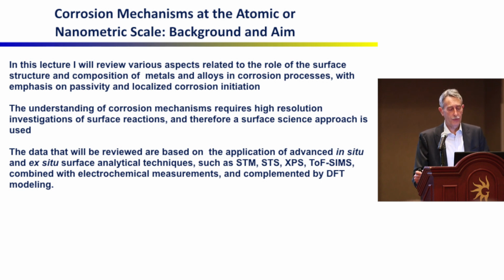So I'm going to show a few data that are based on the application of advanced in situ and ex situ surface analytical techniques, such as scanning tunneling microscopy, scanning tunneling spectroscopy, XPS, ToF-SIMS, which are always combined with electrochemical measurements, either in situ with STM and STS, or ex situ with XPS and ToF-SIMS. And probably I won't have any time to show DFT modeling, but the modeling by DFT is a very important complementary aspect of the research we are doing.